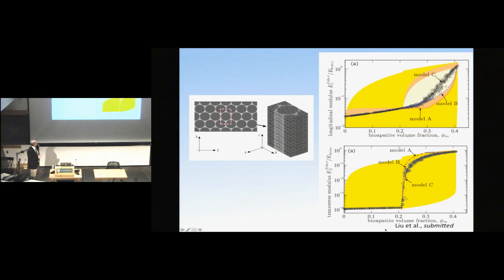And you can see a basic trend that shows up. So this orange envelope is the Hashin-Shtrikman bounds, the tightest bounds you can possibly get on stiffening that result from two materials when you don't know anything about the structure of those materials. And the addition of mineral follows this lower bound all the way up throughout the accretion of mineral on the inside of fibrils. And then the bounds change once material starts to accumulate on the outside.